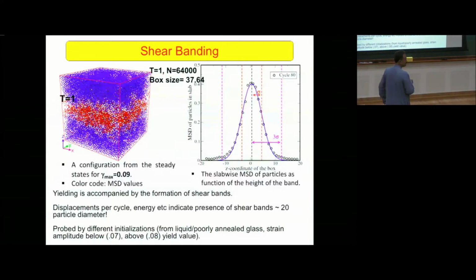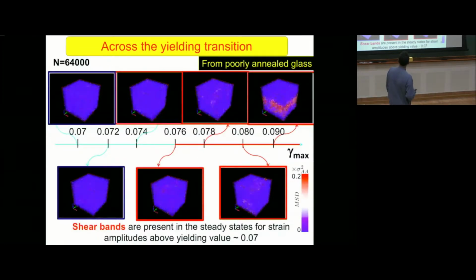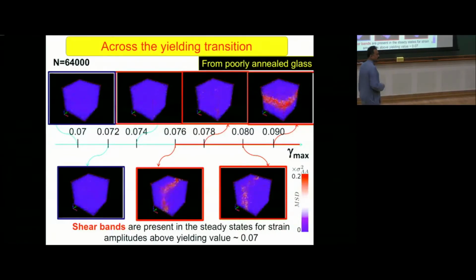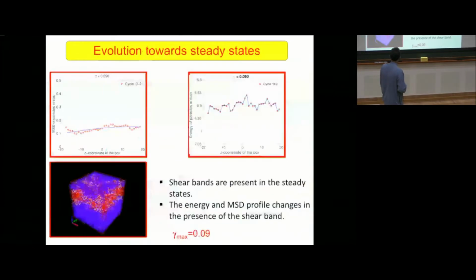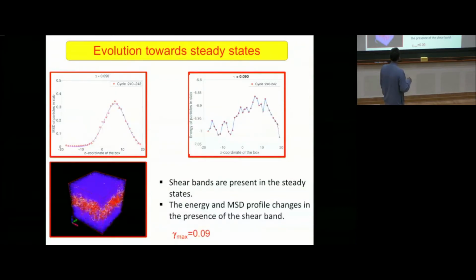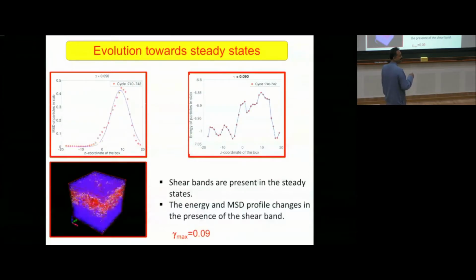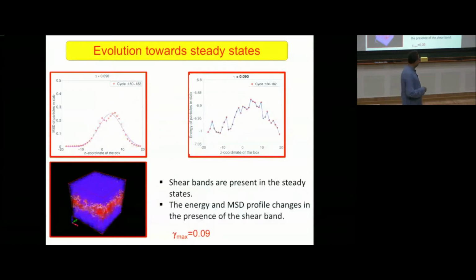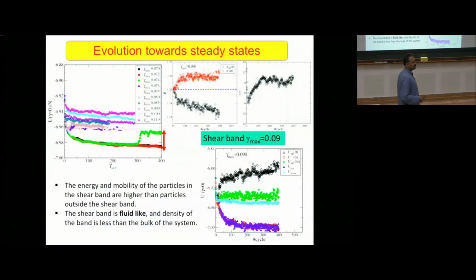So here is what we find in terms of shear banding. You basically find above the yielding strain that displacements from cycle to cycle of particles become localized in some region of space, and that's what is shown in red here. And this is just a fun set of movies to show that this is happening. What you're supposed to pay attention to is the boxes. All the red guys are eventually going to yield, and in these low amplitude simulations you don't see yielding, and therefore no shear banding, but I won't wait for that. One thing important to note is the location of the shear band, as measured by the displacement of particles, is correlated with the energy of the system in that band, but this is the best part.